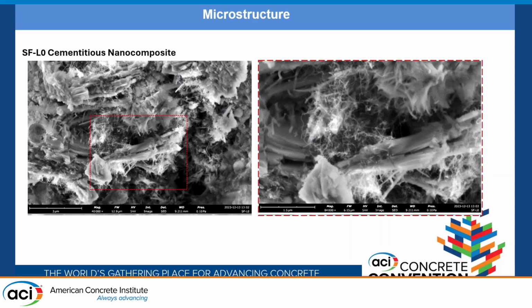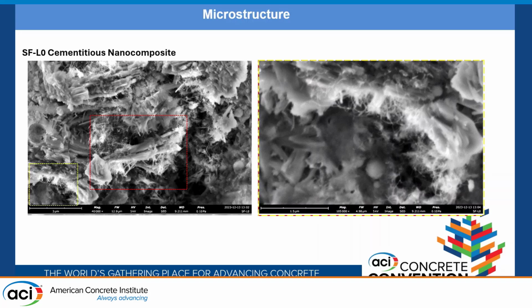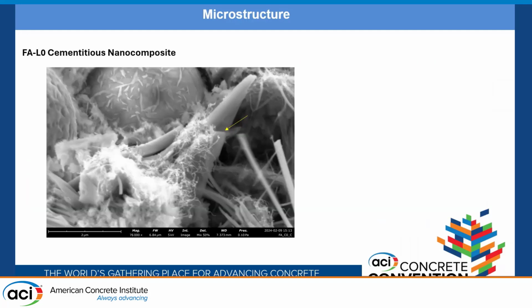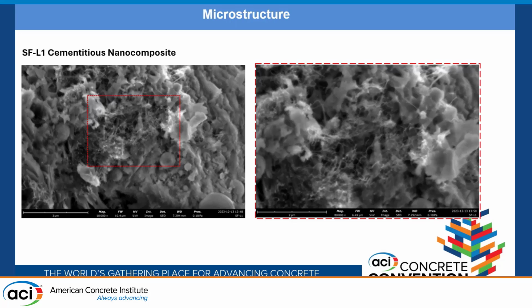And then we did try to find evidence under the SEM to look at the dispersion. This is the case where we don't have any latex and emulsification process, and we still see agglomerates of CNTs and bare spots. Just showing a couple of examples here, and you can see in the background there's not much CNT present. And this is the case that carries fly ash. The fly ash surface is very clean, and you have large clumps of CNT forming nearby, which indicates it does not disperse well in those cases.